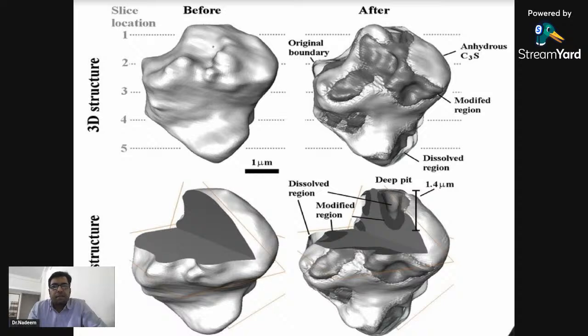If you again further look into that particle, one is a typical particle of say 2 or 3 micron, and once it gets reacted with water, slowly and slowly you will find this is anhydrous unreacted tricalcium silicate. This part is reacted, and slowly if you cut deep inside the particle, you will find this is how it starts getting reacted. But a lot of shrinkage, a lot of pores are happening in this reaction.